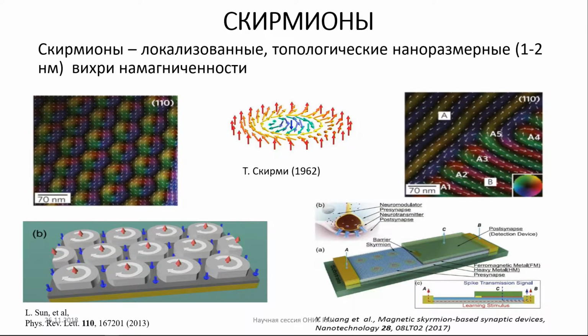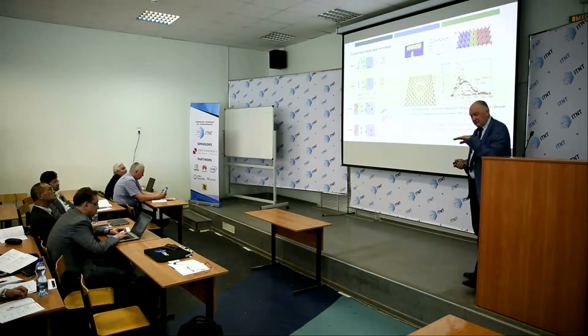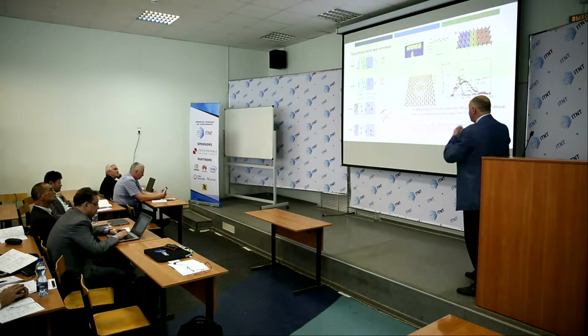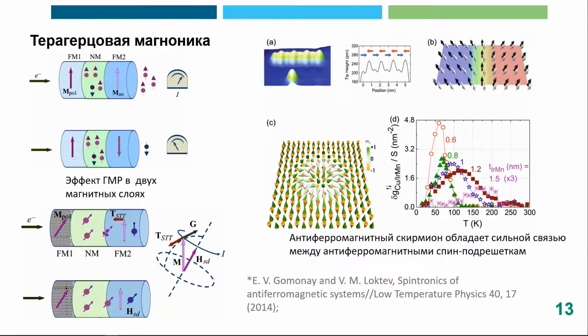Since the magnetization is in one strong direction, for example, a skyrmion in one topological patch has the magnetization up while all the material has the opposite direction, down, you can use these skyrmion elements as memory units, for example. And they have very peculiar forms. Their shape and magnetization can be managed by an external magnetic field. Since the thickness of the material is very small, anisotropy has a very strong influence there. Therefore, by very small magnetic fields, like only a few oersted, you can manage the size of the skyrmions and their movement in these magnetic materials.